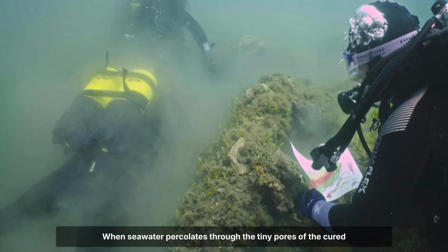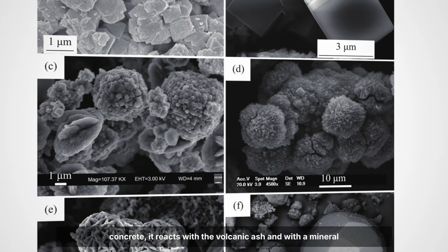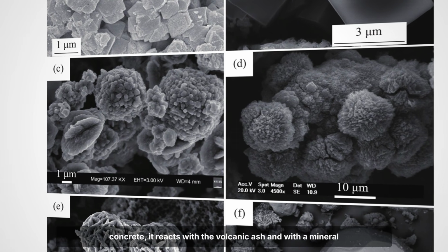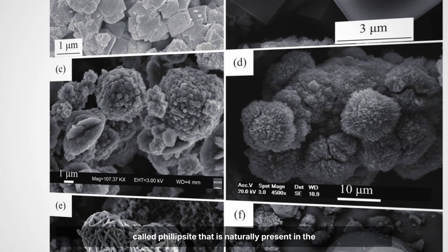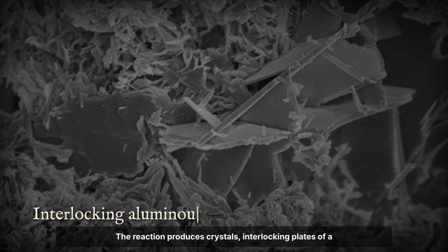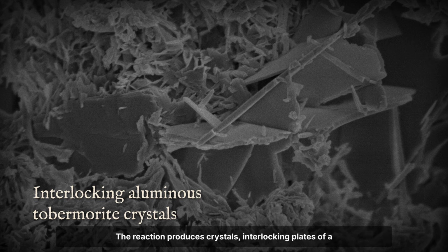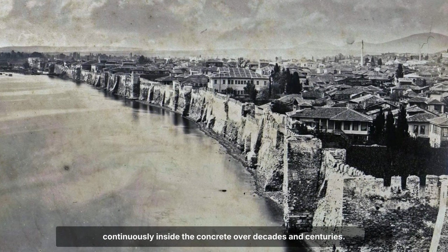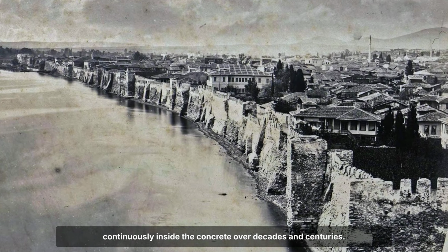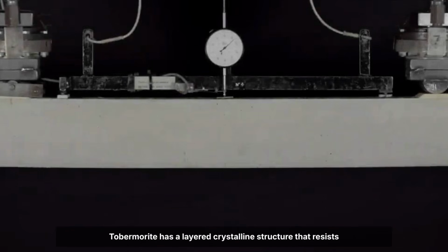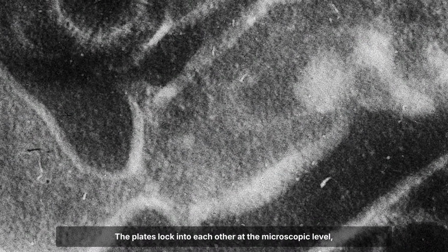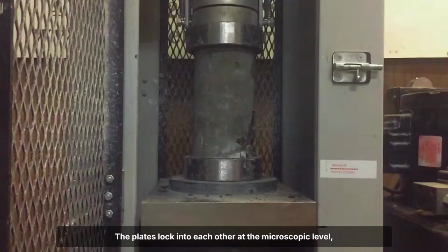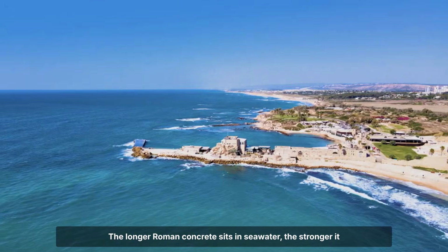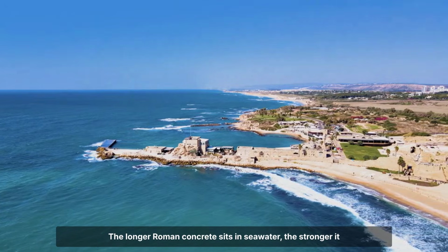When seawater percolates through the tiny pores of the cured concrete, it reacts with the volcanic ash and with a mineral called philipsite that is naturally present in the aggregate. The reaction produces crystals, interlocking plates of a rare mineral called aluminous tobermorite that grow continuously inside the concrete over decades and centuries. Tobermorite has a layered crystalline structure that resists fracturing. The plates lock into each other at the microscopic level, binding the surrounding matrix tighter and tighter with every passing year. The longer Roman concrete sits in seawater, the stronger it gets.